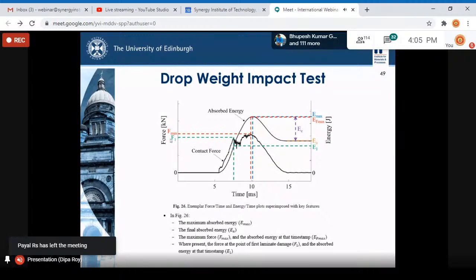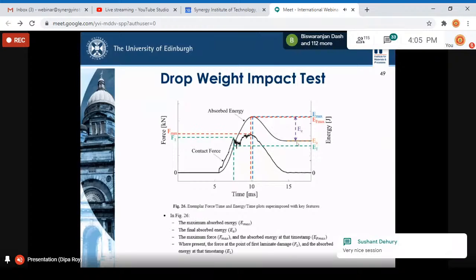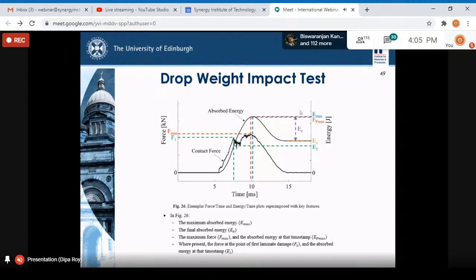In drop weight impact, we can get the absorbed energy as well as the elastic energy. The more absorbed energy, the more the material is able to absorb energy, whether via matrix cracking, debonding, or some deformation. And the elastic energy is what comes from the rebound of the impactor tip. So this is the standard curve we get from a drop weight impact test.